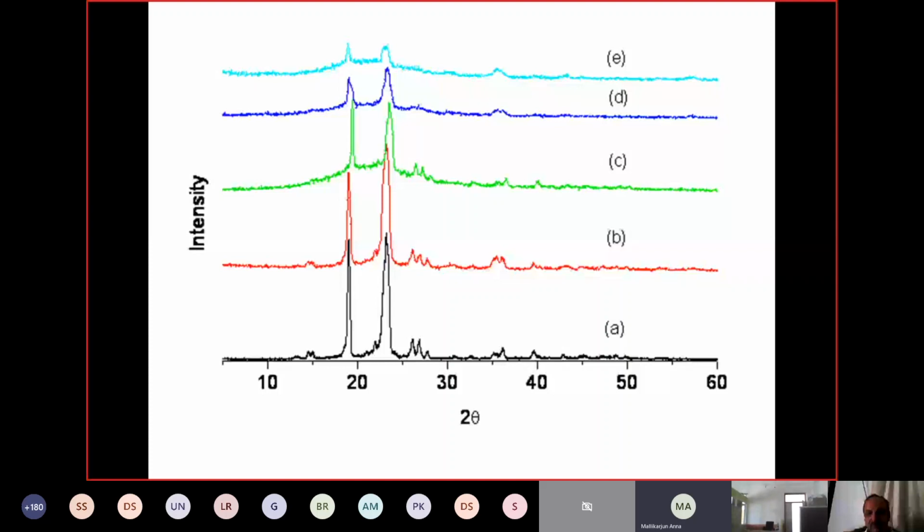Here, figure A is for the pure PEO, B is for the PEO lithium salt, where we added Fe3O4. So C, D and E are the Fe3O4 nanocomposite materials. That means for the same amount of PEO LiClO4, we added different percentages of nanoparticles. So you see here, this peak is shifted and its intensity is also decreasing. That means not only the salt, whatever nanoparticle we added to this polymeric material is also disrupting the crystal nature of the polymer. That is very important here.